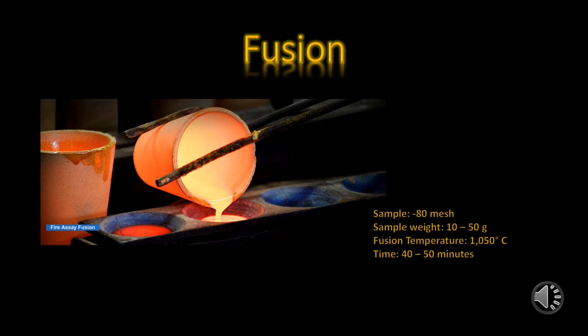The fusion process is simply performed by taking anywhere from 10 to 50 grams of material, which is pulverized or screened to -80 mesh. This could be your concentrates or your sample. This is then mixed with the right amount of flux material to create what is known as the charge. This charge is placed into a suitably sized crucible and then melted in a fusion or muffle furnace at a temperature of about 1050 degrees centigrade for about 40 minutes until it's completely molten.